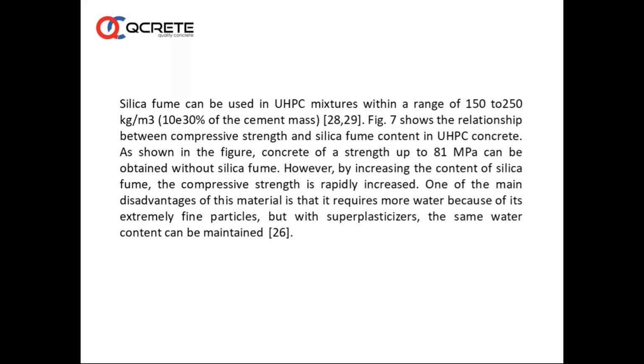And we have seen the relationship between the compressive strength and silica fume content in UHPC concrete. As shown in the figure, concrete strength of 81 MPa can be obtained without microsilica. However, by increasing the content of silica fume, the compressive strength is rapidly increased. One of the main disadvantages of this material is that it requires more water because of its extremely fine particles, but with superplasticizer, the same water content can be maintained. So microsilica, as we know, is a water-hungry product. It kills the slump. It reduces slump from the general slump that we get without microsilica.